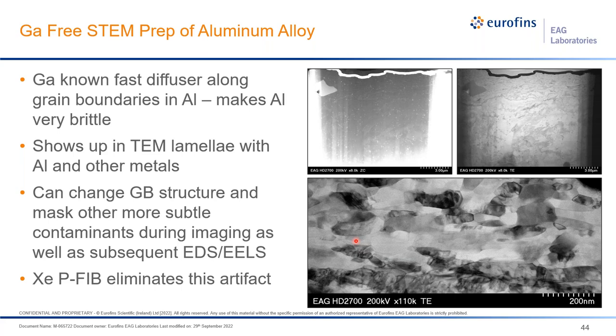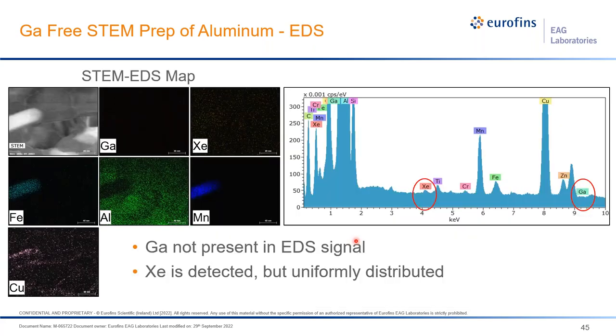And essentially, it can change the grain boundary structure and mask other subtle contaminants you might be looking for at grain boundaries using EDS or EELS. And so xenon eliminates this artifact. So this is just a quick STEM EDS map of the grain structure in this region of the sample.